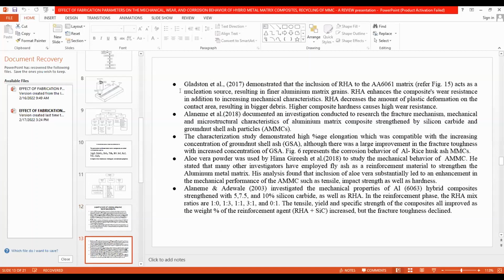So you have the rice husk ash. Rice husks have also been included in the 6061 aluminum alloy, which acted as a nucleation source, resulting in finer aluminum matrix grains, and even the wear resistance, in addition to the mechanical characteristics, has been improved. And you have the Alaneme et al.